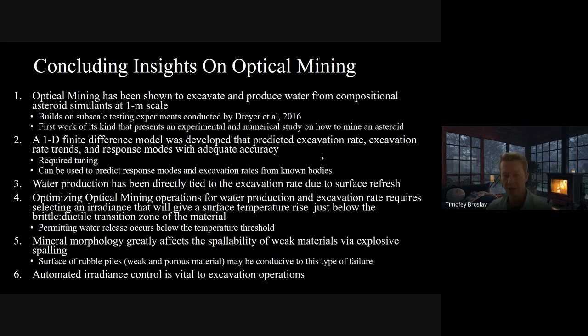And it can be used to predict response modes and excavation rates from known bodies, as well as how to optimize for excavation rates. Water production has been directly tied to excavation rates from surface refresh. Also, there were things learned about how to optimize this process. It requires an irradiance range that will give a surface temperature rise just below the brittle-ductile transition zone of the material, as long as the water release from the minerals occurs well below this temperature threshold.